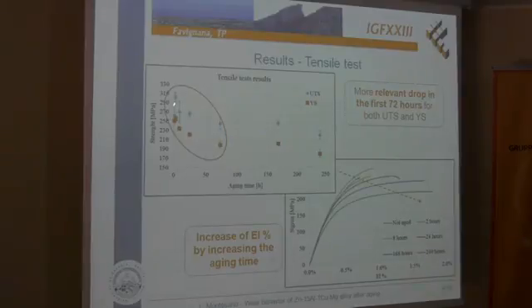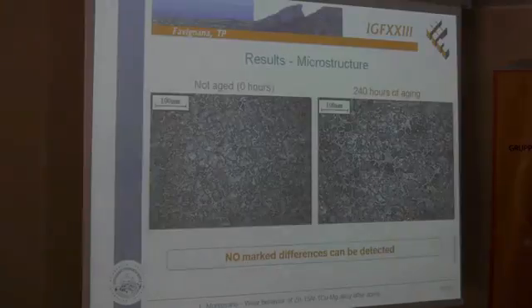So both UTS and YS decrease mainly in the first 72 hours, and then the material seems to reach a stable condition. As the UTS decreases, as visible in this graph, the elongation increases, a sign that the material becomes more ductile. We have to consider that the maximum elongation is around 1%, so the material remains not a real ductile material. The main behavior remains very brittle.